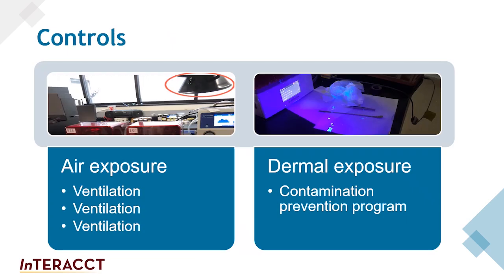The results for air exposure measurements taken for this process were uniformly low. This was partially due to the low volatility of the resins, but also to the fact that the laboratory had 9 air changes per hour of general exhaust, as well as a dedicated local exhaust ventilation hood positioned over the printer. With the persisting unknowns about the risk associated with this process, particularly the nanoparticle emissions, ventilation is the best control that can be used to mitigate air exposure. There aren't really any good alternatives.